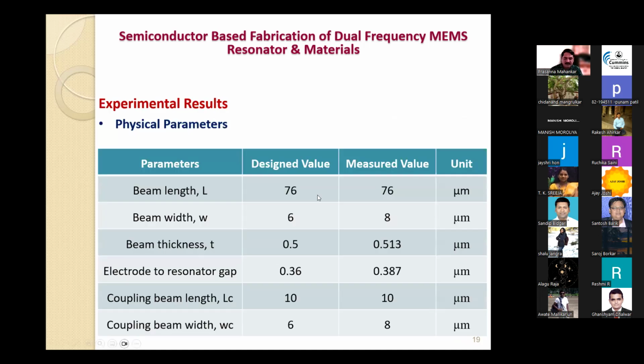Now let us see the physical parameters that we have got in this case. The beam length, we designed for 76 micrometer, and we got 76 micrometer. The beam width was designed for 6 micrometer, and we got 8 micrometer. The desired thickness was 0.5 micrometer, and we got 0.513 micrometer. The resonator gap was designed for 0.36 micrometer, and what we got is 0.387 micrometer. The coupling beam length was 10 micrometer, and the width was 6, which we got as 8 micrometer after actual measurement, compared to the design values.